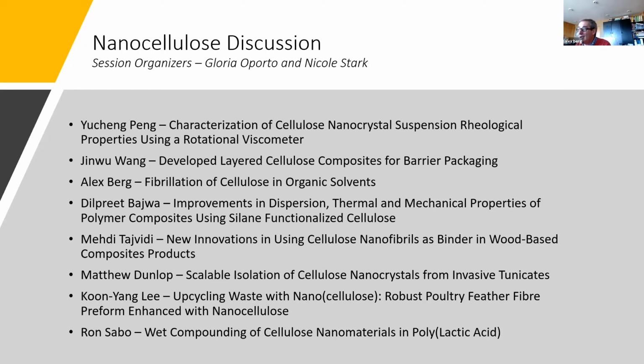If a higher specific surface is available, the degree of substitution rises. And the fourth result, and in our opinion the most important, the reinforcing action of nanofibrils in commercial urea formaldehyde resins is clearly superior if we fibrillate the fibers in acetic acid in comparison to the water media.